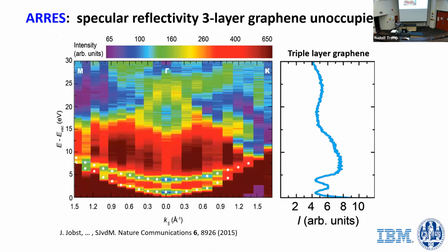And that's shown here. So here's the same curve. You see we have three layers of graphene, two minima, and plotted here as a function of energy at normal incidence. So K parallel is 0. If you now tilt the beam to measure that as a function of incident angle, then we find that these states are not at constant energy, they disperse, right? And if you look at this dispersion, so this is K parallel, the in-plane momentum of the electron. And this is the energy.